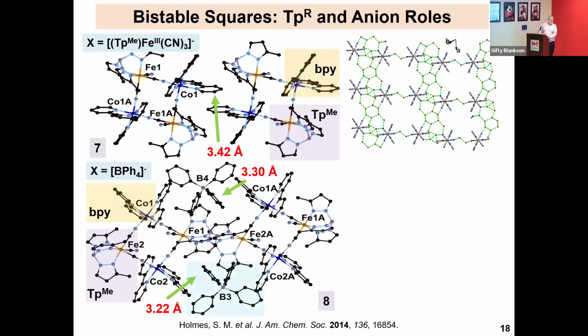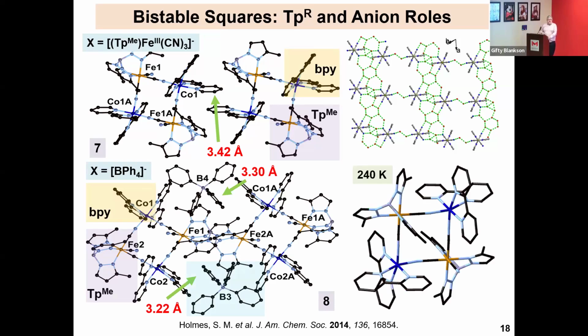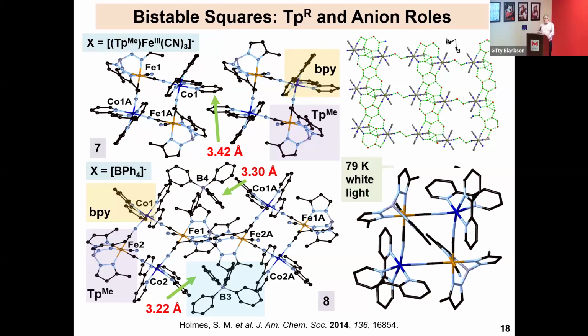All right. More simply, we can use tetraphenyl borate to substitute those tricyanoferrate anions. You get a different structure, but you have molecular squares shown here, and tetraphenyl borates there. All right. And so for the first time, we were able to show not only can you get an X-ray snapshot as a function of temperature, you can also get it as a function of light. Right, so at 240, it looks like that. At 120, it looks like that. Again, things are moving. With light, you also see corresponding changes in the structure, all of which are reversible, depending on whether you obtain the data in the presence of light or absence, and at what temperature you obtain the data. So again, we're reaffirming that these compounds are accessible by temperature changes, light, it's all electron transfer.